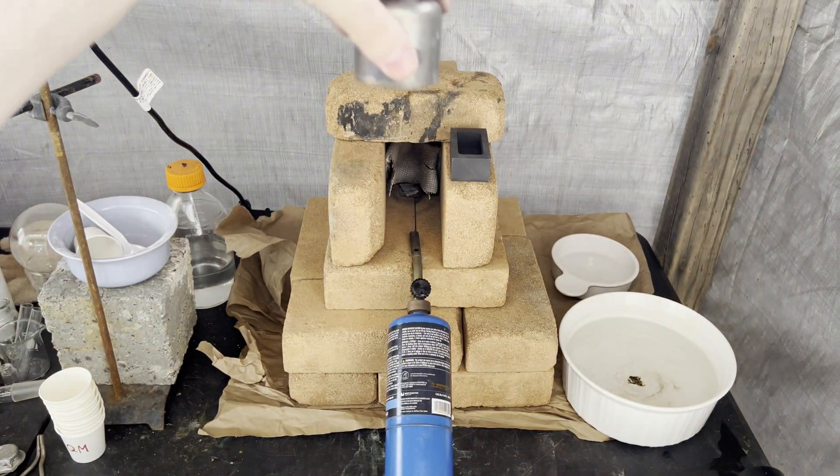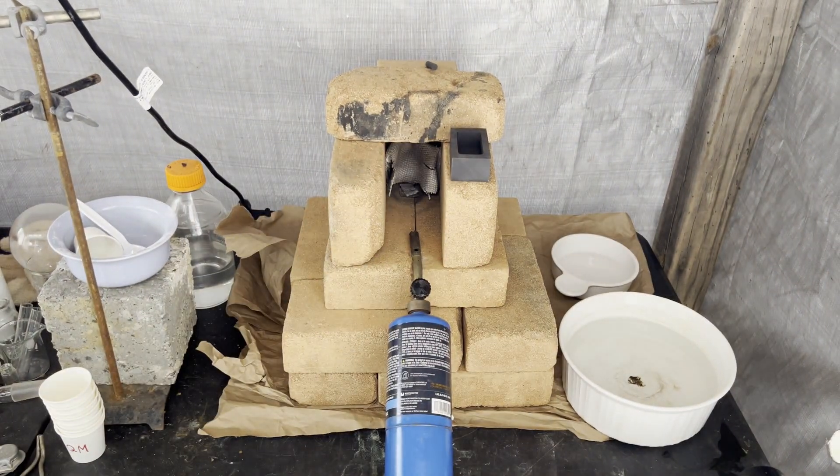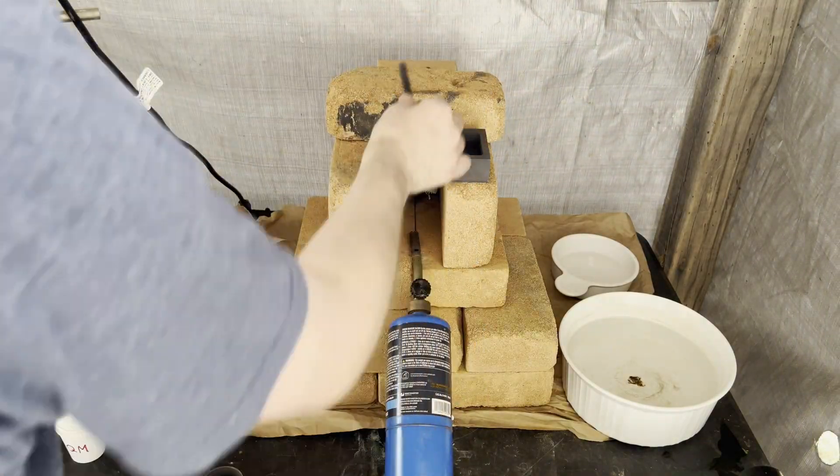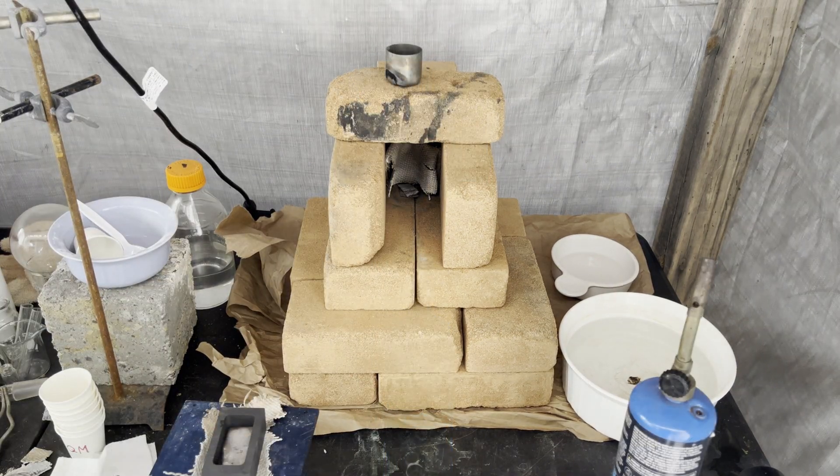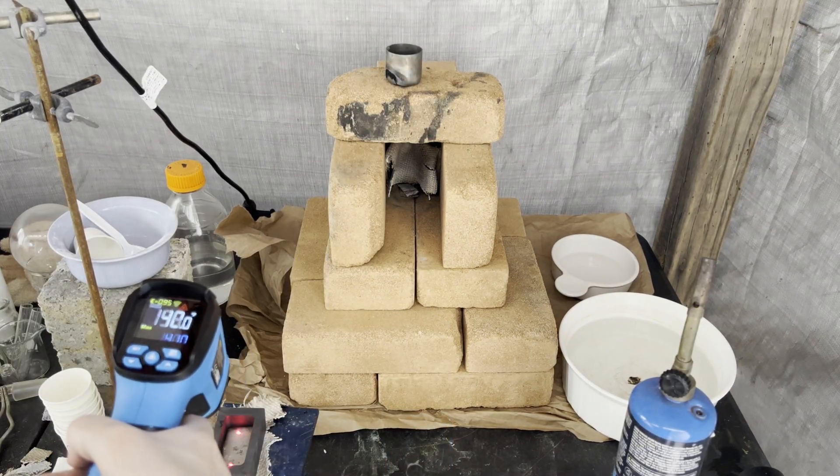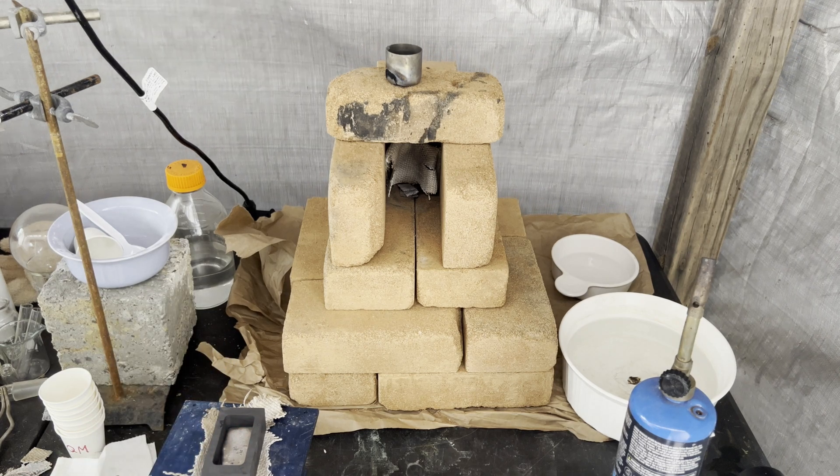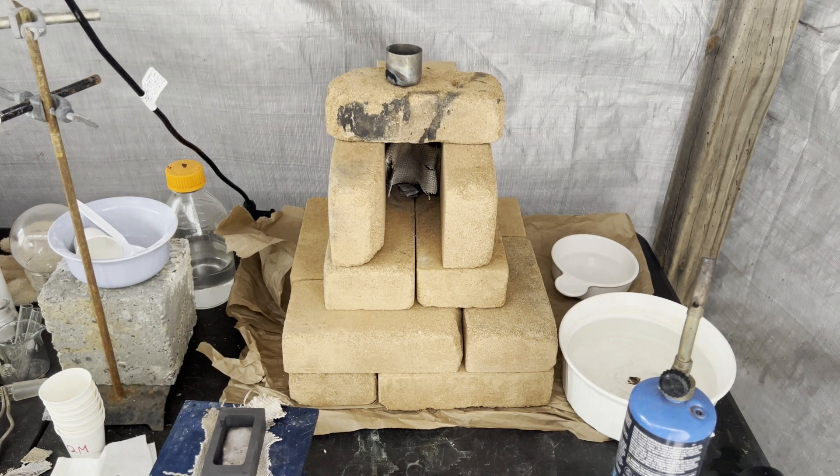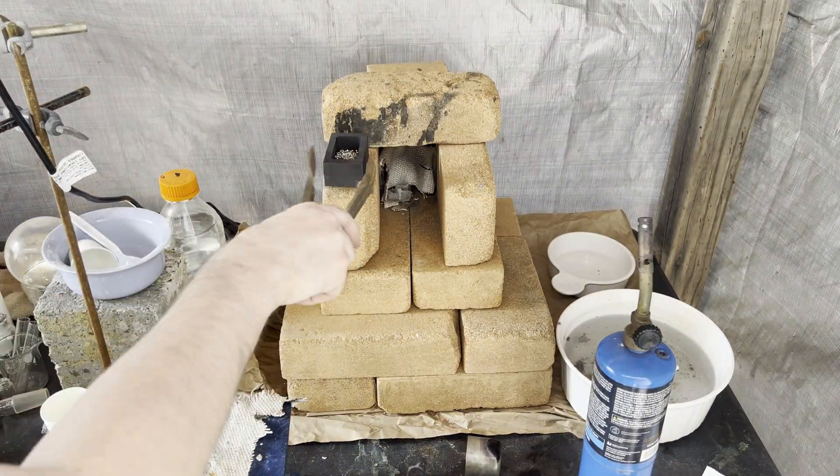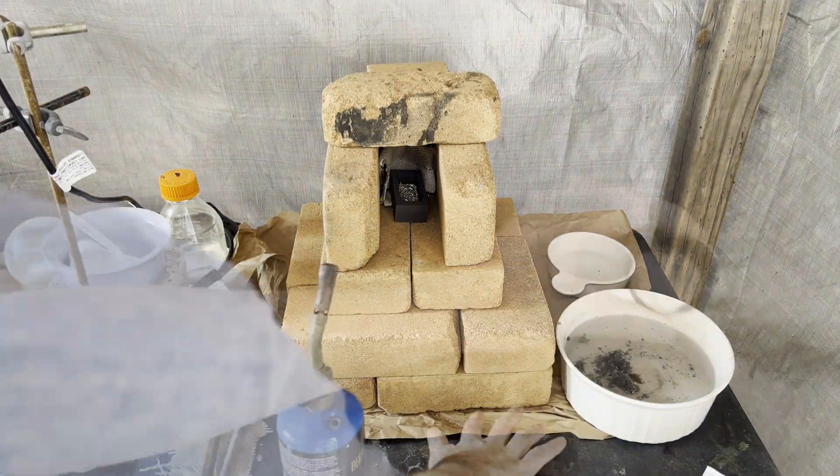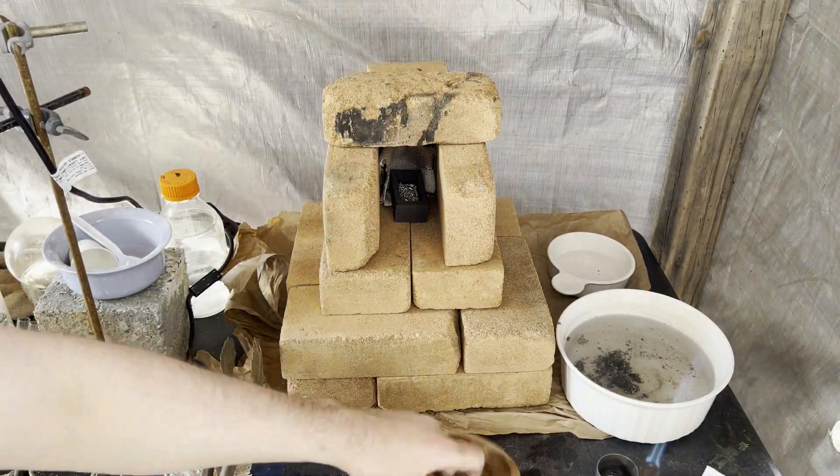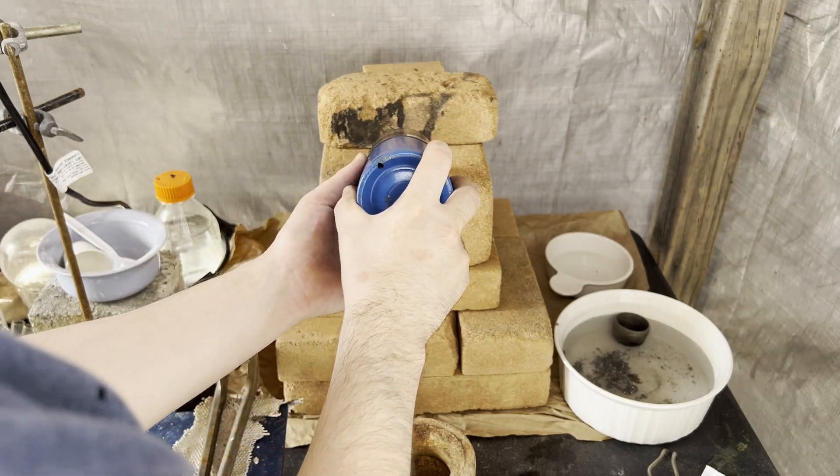After that I realized I had to switch things up, but again I lack the proper equipment for this, so I used a graphite ingot mold as a crucible, far from ideal. A cast iron, steel or graphite crucible would be best for pewter melting. I didn't want to order one and wait, so I improvised. The ingot mold worked but it took longer to get good mixing since it's rectangular and the ingots are thin, about four maybe five millimeters thick.